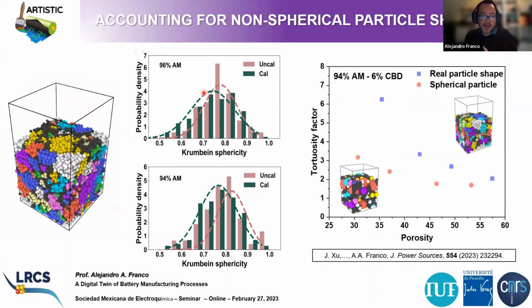With this model, you can also account for the cracking of the particles. This is a paper that is right now under preparation and hopefully will come out soon. It's an extension of this model, which is able to predict under which calendaring conditions the active material particles are going to crack, right? And this is also a problem in terms of manufacturing and producing electrodes in industry, right? How to optimize the calendaring process in a way that you have good electronic percolation between the particles, you don't collapse the pores, and at the same time you don't crack the active material particles.